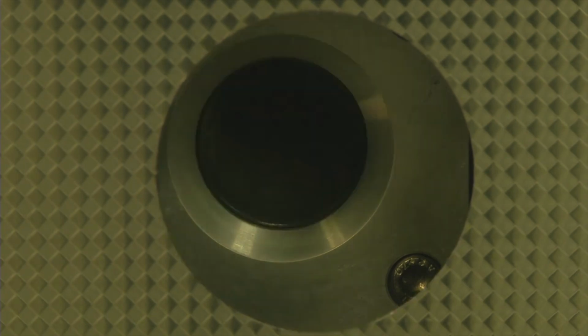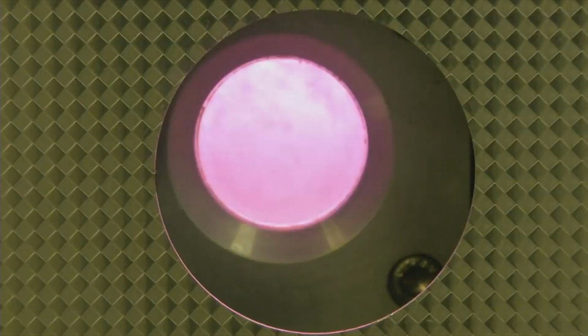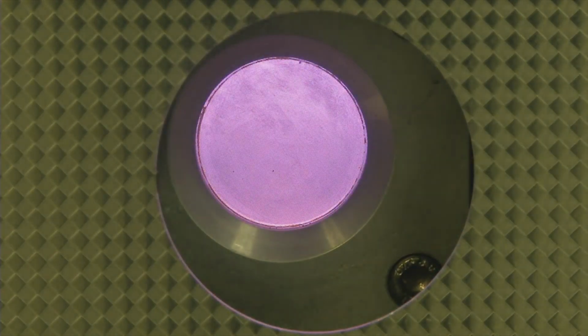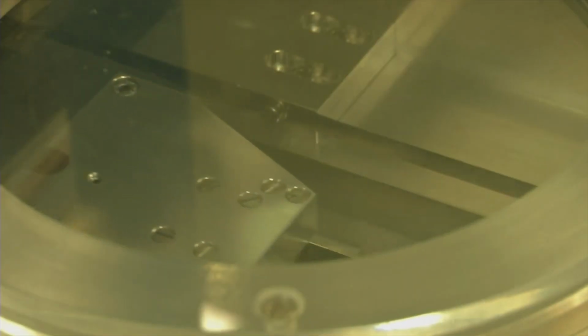Once this is done, again the flash goes down, and now it comes back. In this case we are etching photoresist, right? We are removing photoresist by using oxygen plasma, and the oxygen plasma cleans up all the residues that you have on top of your wafer, and now the cantilever is clearly made without any photoresist. After this process you have a clean wafer. Once the process is done, we are going to retrieve the wafer.